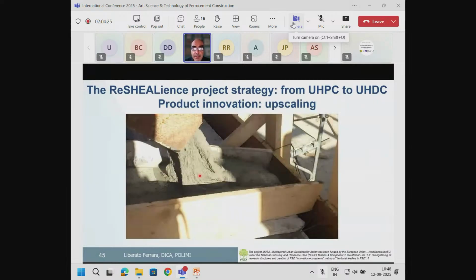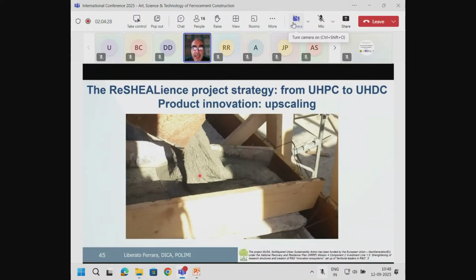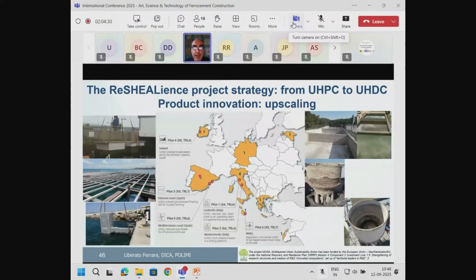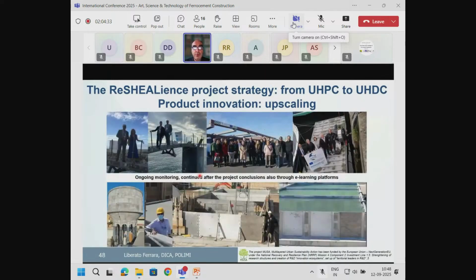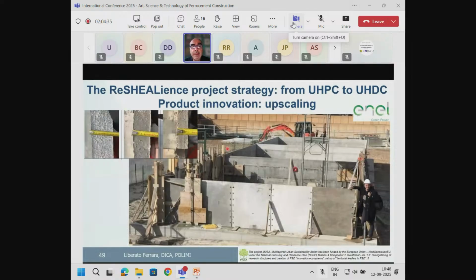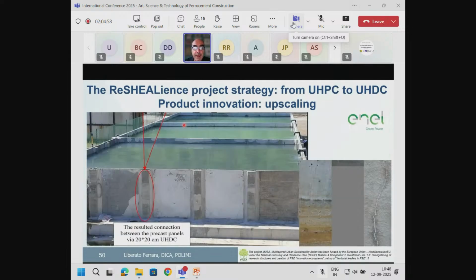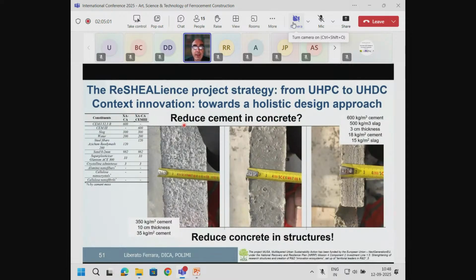So we scaled up. This was a real job site. We scaled up to real volume, real casting volumes. And I want to show you some pilot examples that we built using this material. This is a basin. And here on the top left, you have the conventional reinforced concrete solution, which is 10 centimeters thick. But with our materials in precast slabs, we were able to go to, you see here, 3 centimeters thick. So very thin structures for this kind of application, and examples of the load test